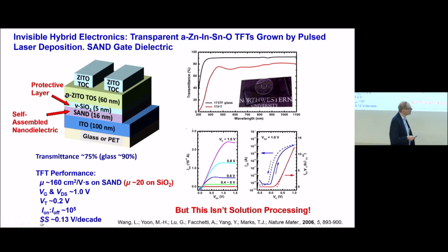I'm going to give you an abbreviated discussion of some of these points, but here's one of the first things we did. This is a transistor where ITO is the gate electrode. There's glass here, or PET. This is a gate dielectric we've developed, a self-assembled nanodielectric. And here's the amorphous oxide. This one is zinc indium tin oxide, and we're going to grow it by pulsed laser deposition. This is a matrix of 100 transistors.